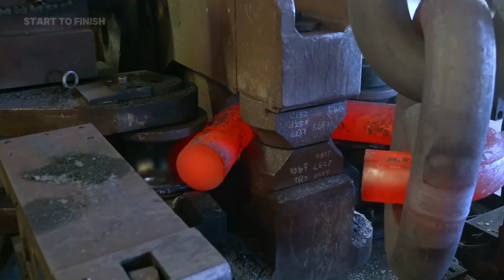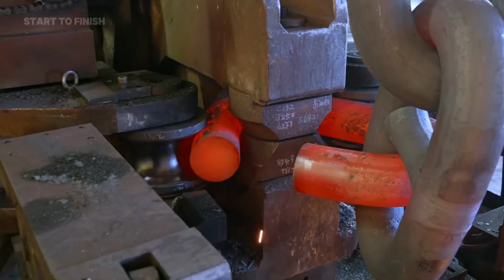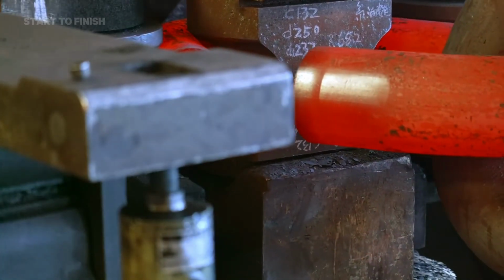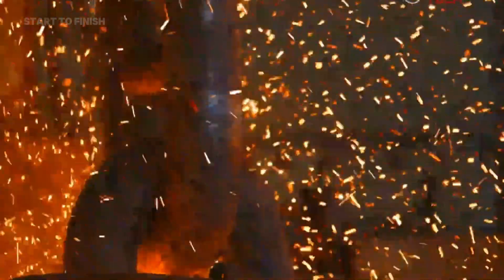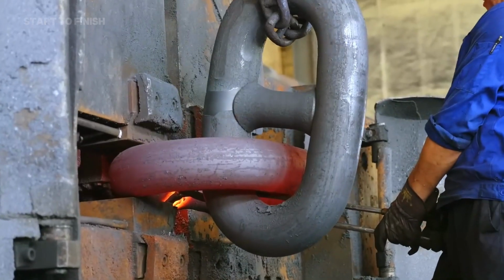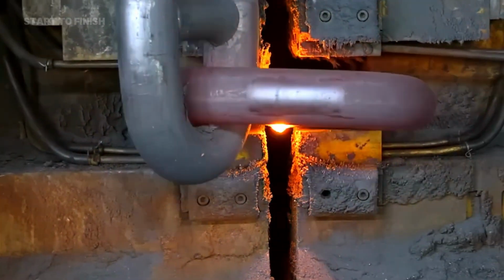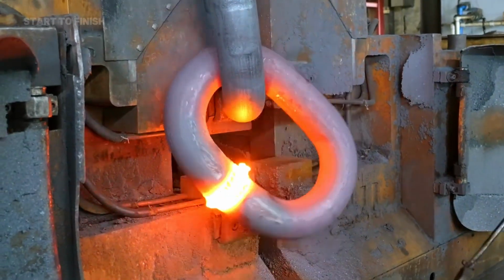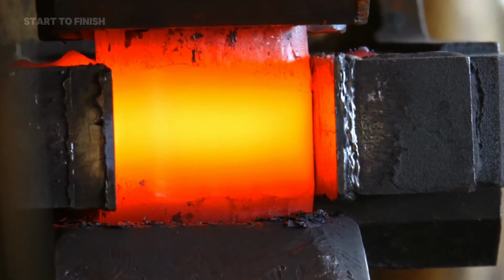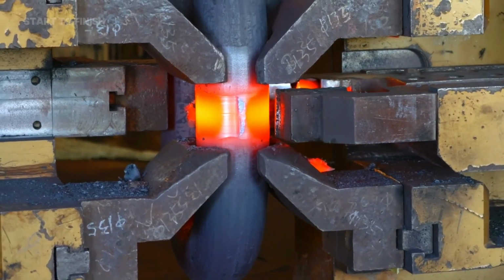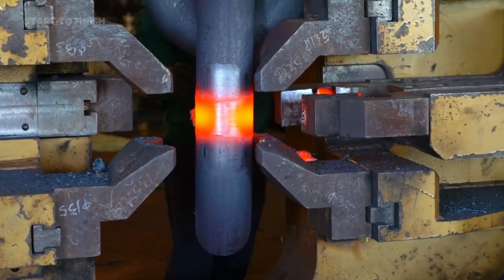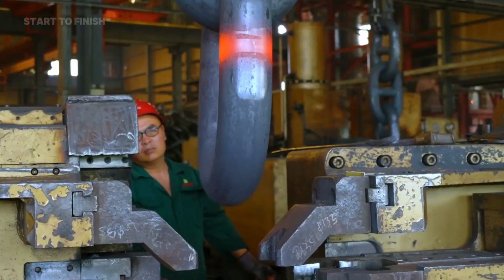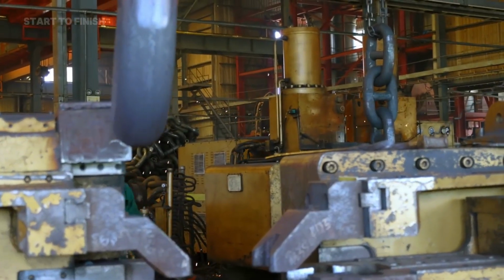A single link failure at sea could mean catastrophic loss, so tolerances are measured to millimeters. Each formed link is overlapped with another, ensuring they interlock seamlessly before being closed by forge welding. The heat and pressure fuse the ends permanently, creating a joint as strong as the parent metal. For anchor chains rated for offshore oil platforms or super tankers, this joint strength is tested repeatedly during production. The newly forged links are now one continuous chain, still red-hot and flexible.